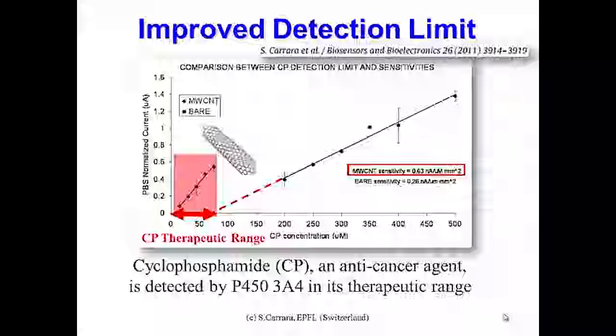this graph shows that the presence of the carbon nanotubes in the electrochemical interface really puts us in the condition to succeed in detecting cyclophosphamide at the concentrations found in patients. But these experiments are typically lab experiments, so we detect cyclophosphamide in PBS, which is a buffer. That means that we are not measuring the compound in the patient's blood, but just using a bit of water, a bit of salt, and exactly the molecule we want to detect, which is not so fair. So when we work with patients and with the patient's blood, we have tons of other molecules that can interact with our sensor. So, okay, this is a good demonstration of a principle, but now the point is to see if we can really run the business with the patients.